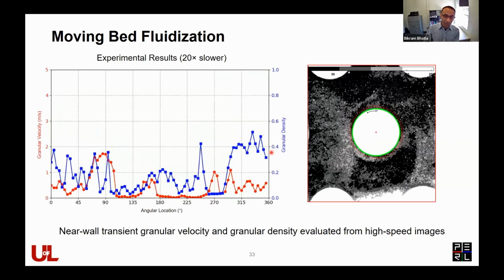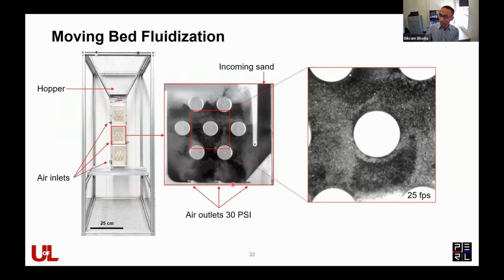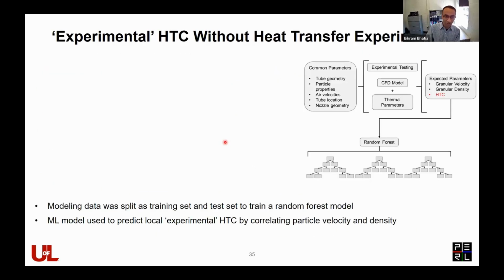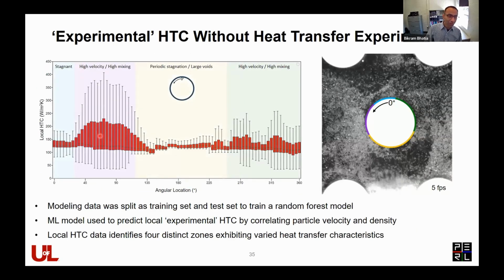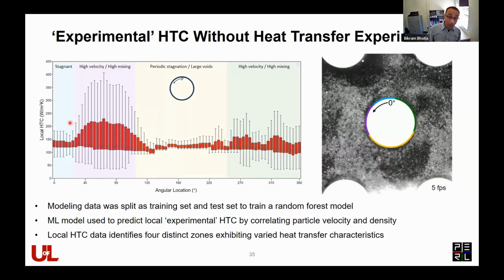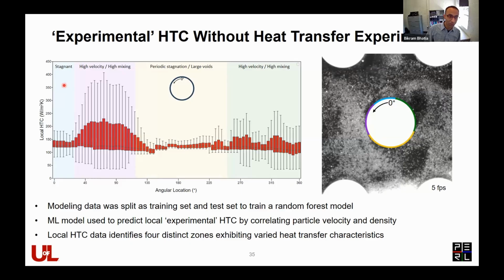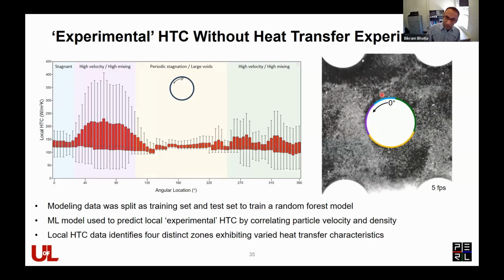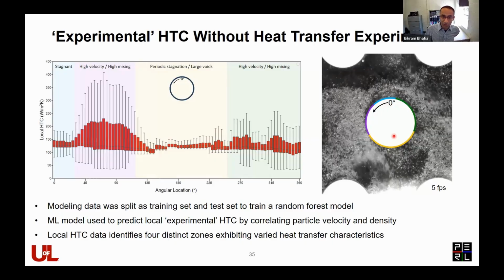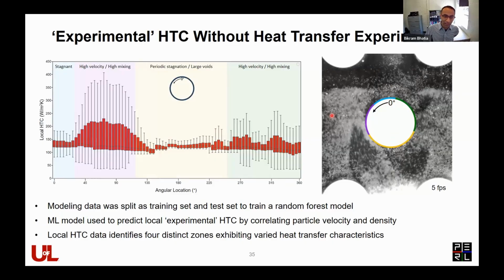we do have this asymmetry in our experimental setup, where the air actually forces the sand to flow in this clockwise direction. So you have slightly higher velocity on the left side versus the right, which is what we see in our heat transfer coefficient data. And we really see four regimes, even in a fluidized system, for this heat transfer coefficient. You have the top regime, which still, despite the fluidization, has a narrow stagnant zone.